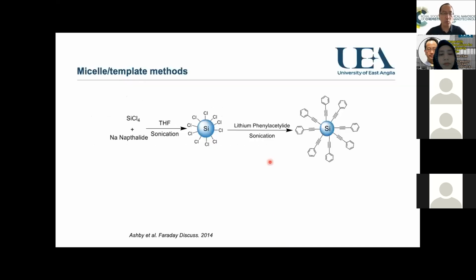One example here is one of the reaction schemes. Using this bottom-up method, we can get phenylacetylene-capped silicon nanoparticles. Basically, you just scale up the reactions from the lab to industry, and then you can get kilograms, tons of this kind of material. Similarly, we have ligand-protected silicon nanoparticles, and we can use different functional ligands to do this kind of work. So that's the second stage we use to scale up the productivity.